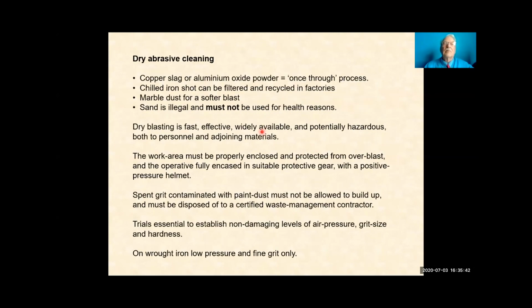Copper slag or aluminium oxide are commonly used as a once-off process. In workshops, we can use and recycle chilled iron shot. You can use softer stuff if you wish, if you want to avoid doing damage to perhaps the non-ferrous metals. You must not use sand. It's illegal because it breaks down and there's a risk of silicosis.